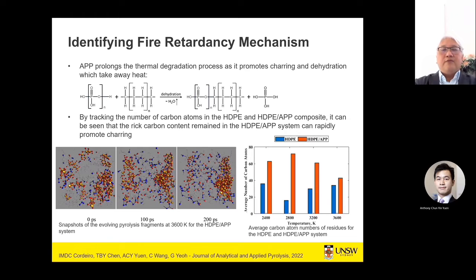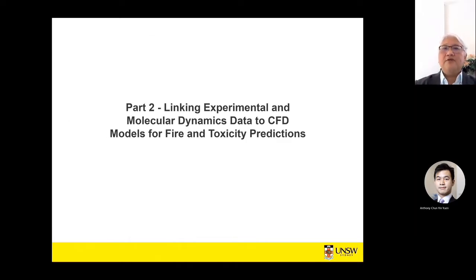as shown by the right-hand figure there. And if we look at the flame retardant mechanism, the first thing that we really notice is that the number of carbon atoms prevailing during the degradation process is much greater than in the original HDPE. That means the material promotes char, which suppresses the degradation and insulates the material from degrading more. Also, APP undergoes a dehydration process, which forms water vapor to further suppress the flammability and combustion behavior. And this is how we get insights into how APP can be an effective flame retardant for flame-proofing polymers.